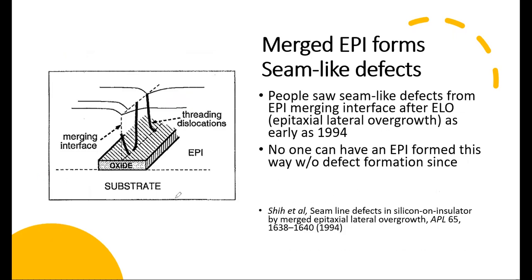Here I present to you a 1994 paper, the ELO, epitaxial lateral overgrowth. So you grow epi from both sides, right? This is oxide, and you grow epi from the trench here, and you merge. When you merge, because there's no perfect match surface, you always have a mismatch. The merging interface always has dislocation. It could be threading, could be something else, could be stacking faults, depending on the conditions you grow, right?